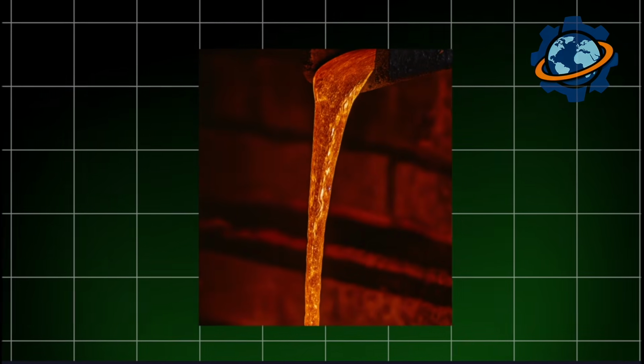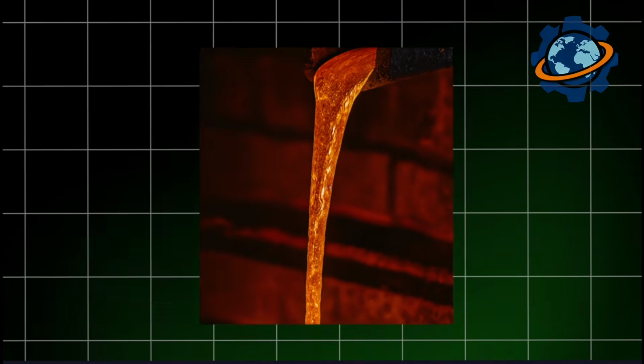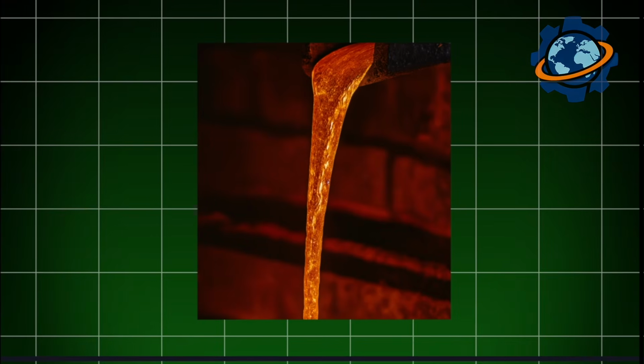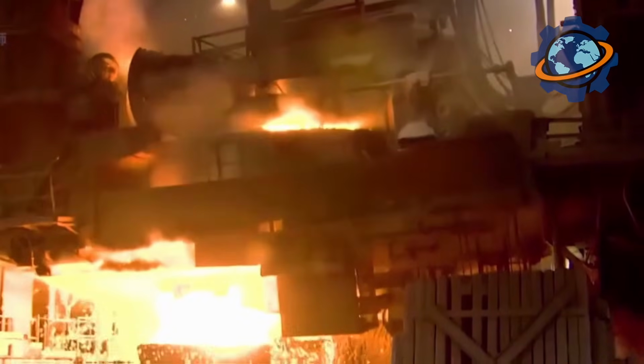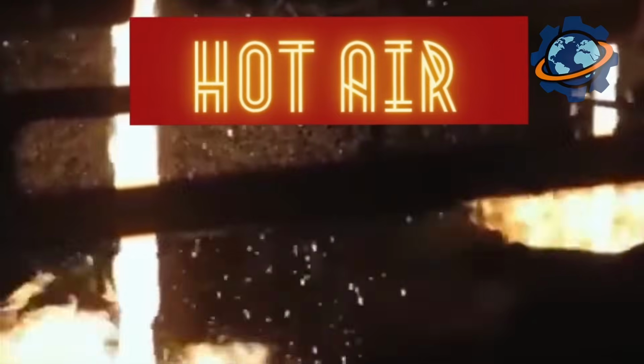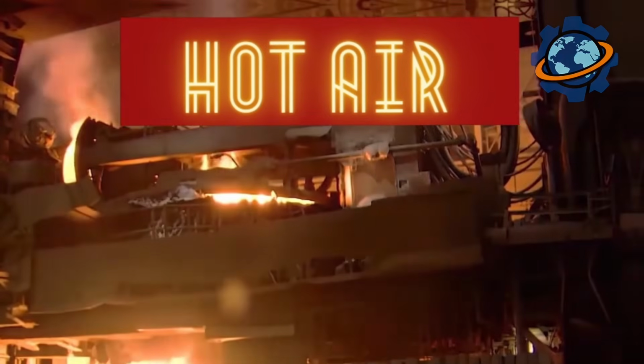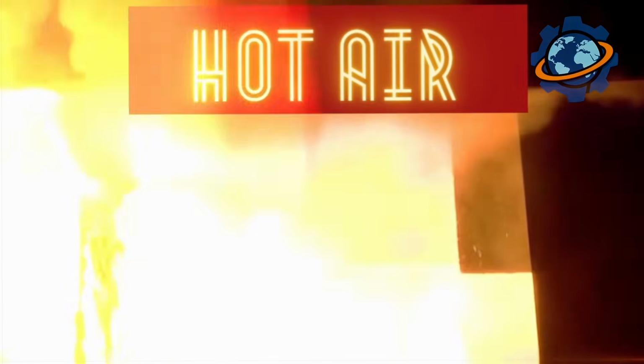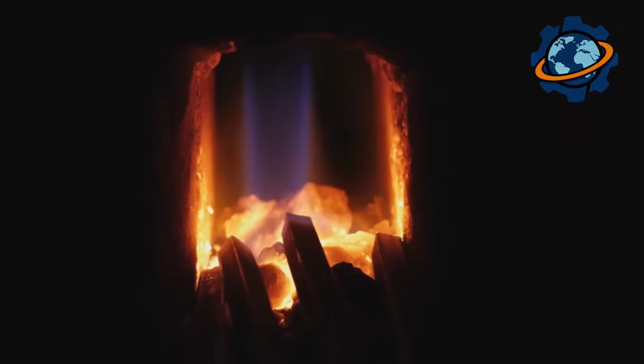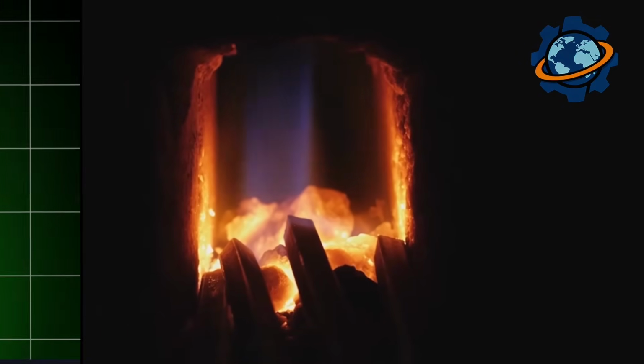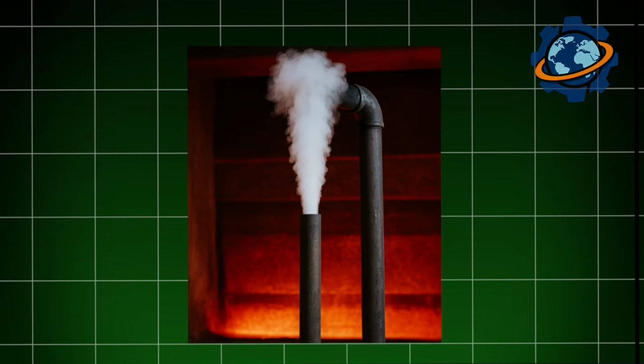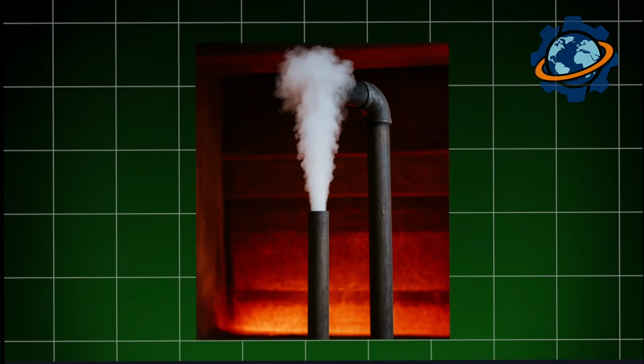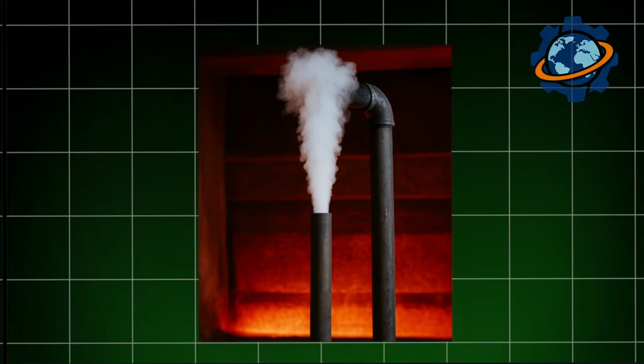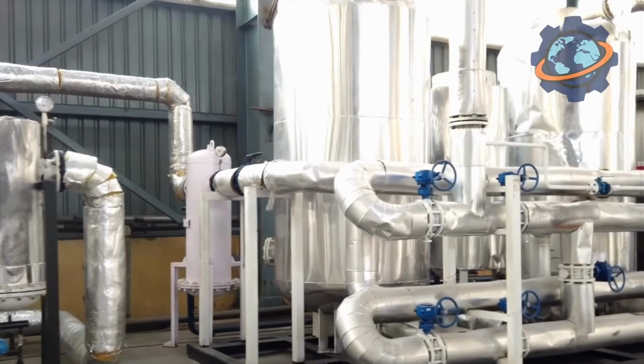At 2,200 degrees Fahrenheit, carbon begins taking oxygen away from zinc oxide. A reduction reaction occurs. But something amazing happens. Zinc doesn't melt. Its boiling point is only 1,665 degrees, but the furnace is at 2,200. So zinc immediately turns into vapor, metallic vapor. Inside the furnace, atoms of gaseous zinc are flying around.